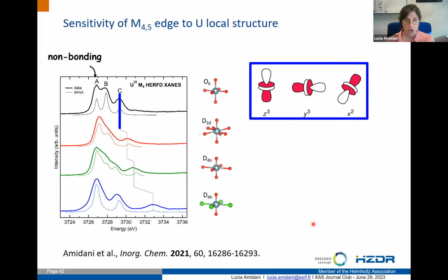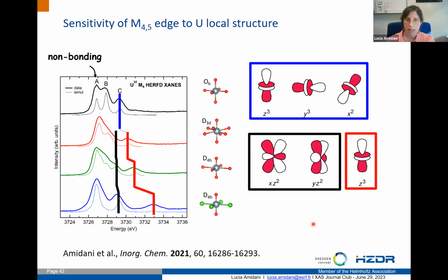The high energy peak, this peak C, which in the case of the uranate is given by the three orbitals pointing towards the ligand, is then split by the compression. And it is here in this region that we expect the effects of covalency or any change of the local environment. What is nice, I think, in this case, is we also try to see what the crystal field approach would give us by using Quanty.